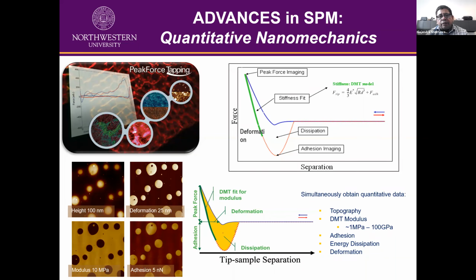In this category, the first one is peak force quantitative AFM, which was developed by Bruker a few years back, and it brought a lot of advances to scanning probe microscopy. In the conventional AFM, you have a contact mode and a tapping mode, where contact mode is mostly used for high resolution and tapping mode is usually used for measuring soft materials. But in peak force tapping, we know that there are two primary causes of tip and sample damage. Any lateral force that the tip exerts on the sample can cause the sample to tear, and the tip plows through the sample.